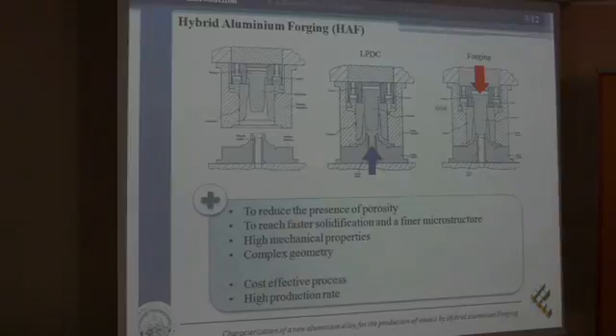During the first one, the mold is closed and is filled as in low pressure die casting. As a second step, the feeder tube is closed, and then the upper part of the mold is used to apply a forging pressure on the material during the solidification, so when the material is not yet completely solidified. In this way, it is possible to reduce the presence of porosity, to reach a faster solidification and so a finer microstructure, and this can help in the improvement of mechanical properties.